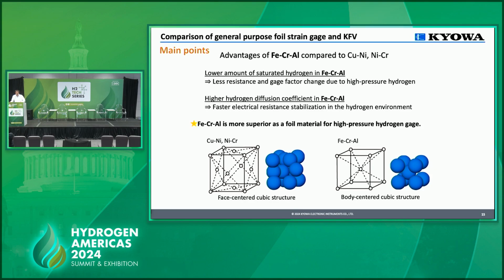These two advantages come from a cubic structure difference between iron chromium alloy and the copper nickel and nickel chromium alloys that are typically used for general purpose foil strain gauges. When you look at the iron chromium alloy, it has a body-centered cubic structure. This geometry provides more pathways for hydrogen to diffuse more easily.